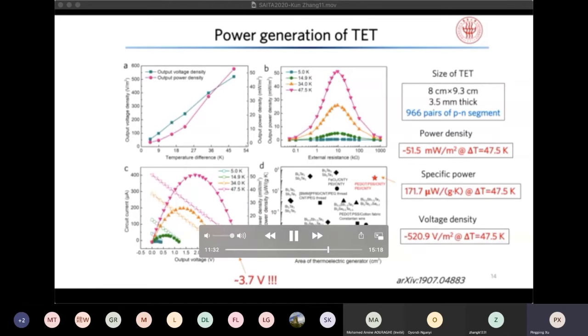We get a high power density of around 51 milliwatts per square meter at a temperature difference of 47 kelvins. With the voltage density about 520 volts per square meter, we can generate 3.7 volts. So this is comparable to that of a lithium-ion battery. And our thermoelectric textile outperforms the majority of textile-based thermoelectric generators, and it is the best one ever reported among organic-based thermoelectric textiles.